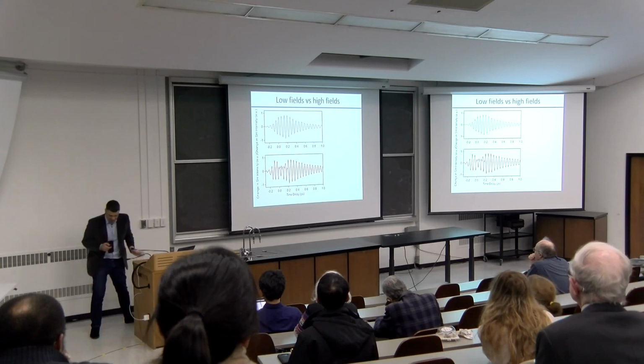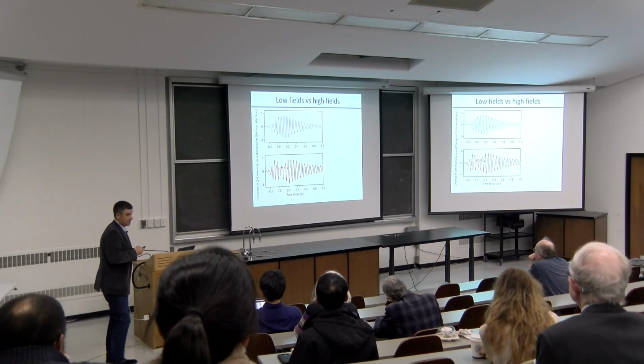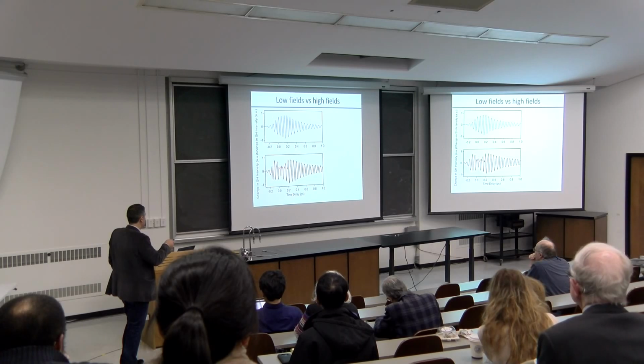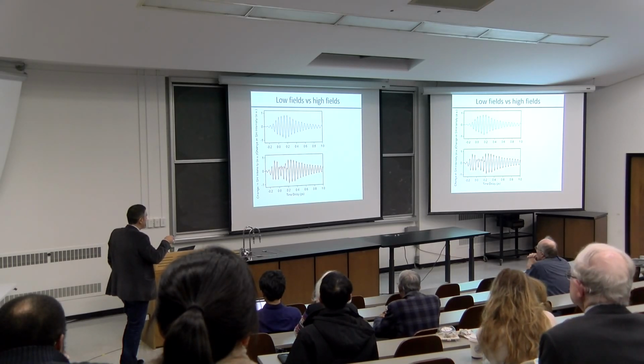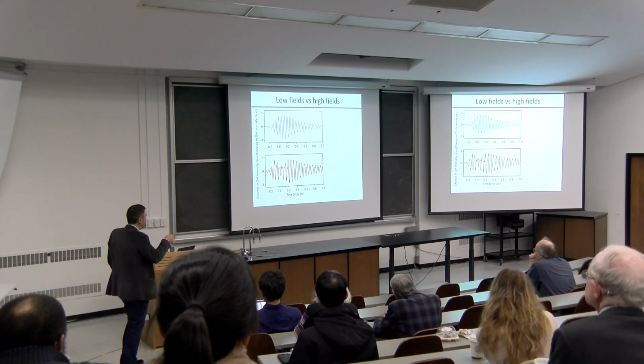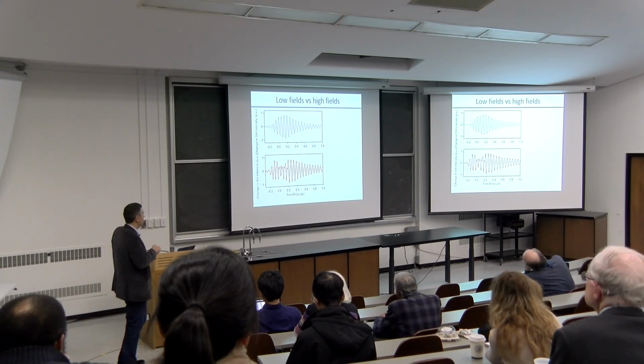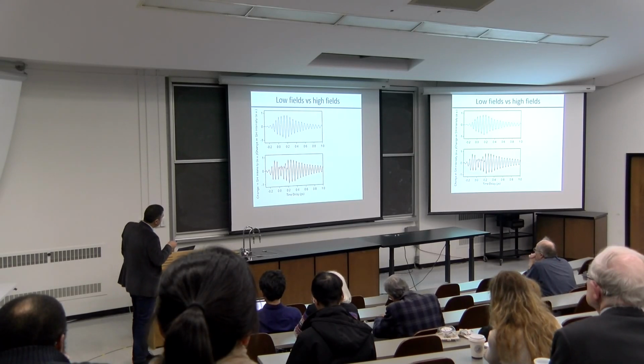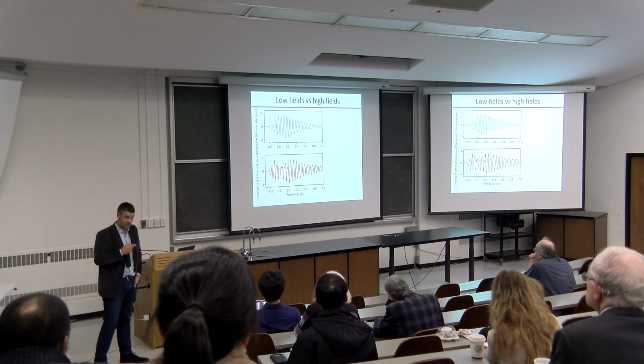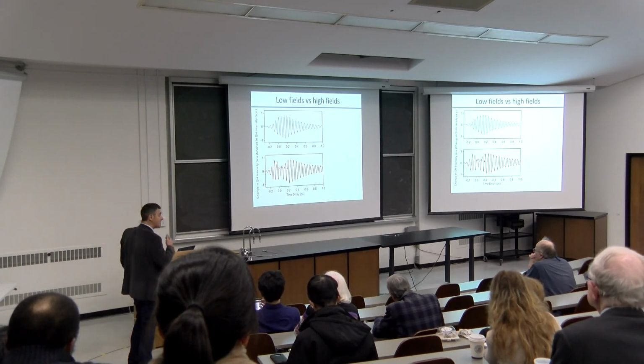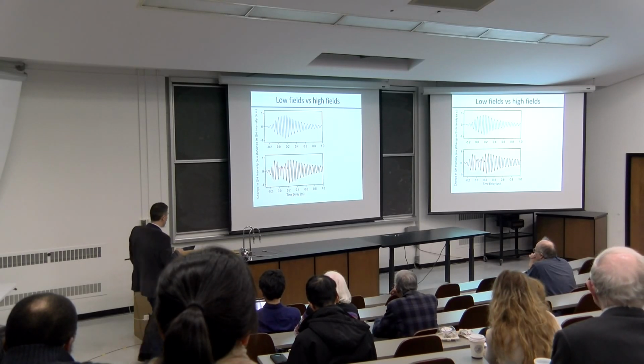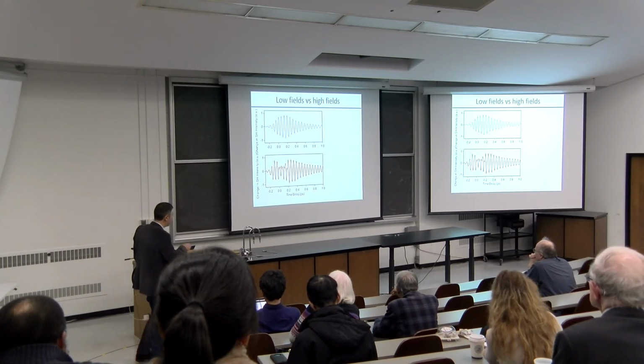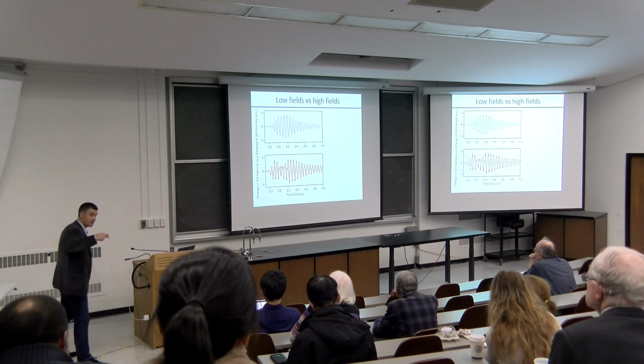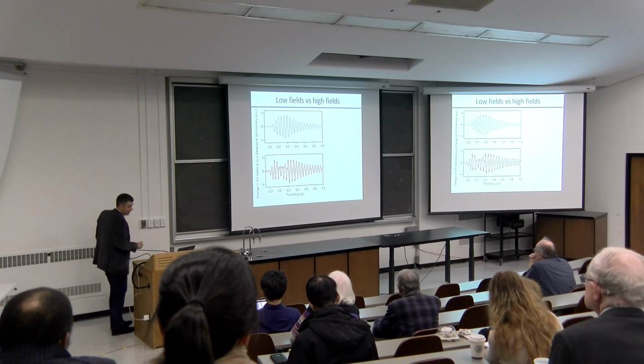Okay, this is data. So if I pump my ferroelectric with a pump pulse that is weak, the response, so this is now second harmonic intensity as a function of pump probe time delay between the field of the pump and the probe. And if the pump is weak, what I will get is a perfectly harmonic, damped harmonic oscillator, which is the same that I promised at the beginning was going to be the linear response of a phonon. However, if I drive the phonon to very large amplitudes, I start getting all sorts of anharmonic responses.